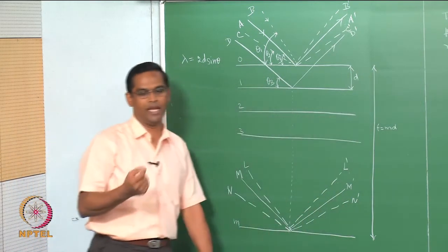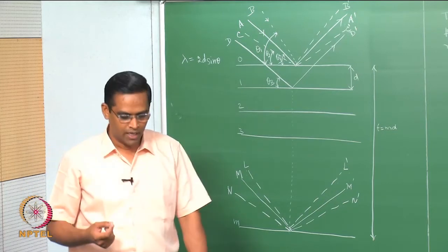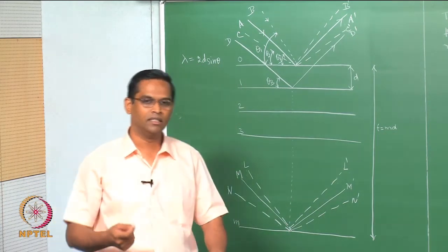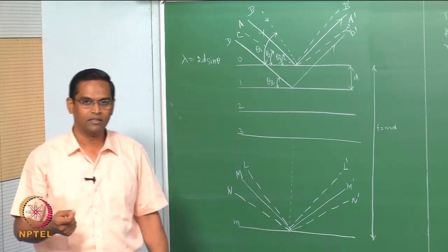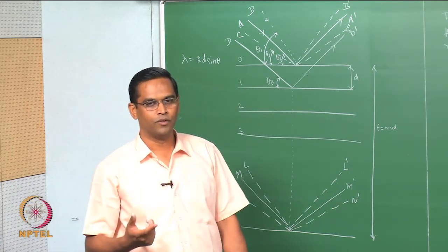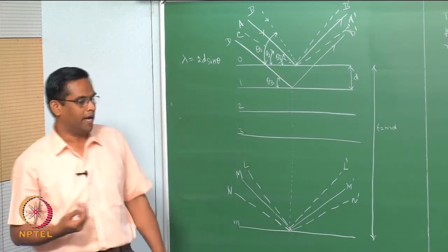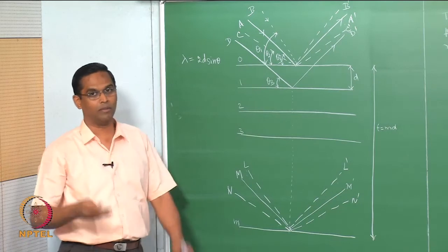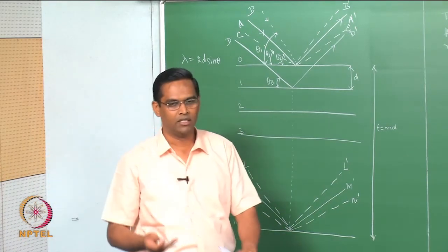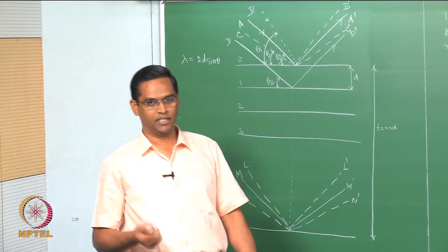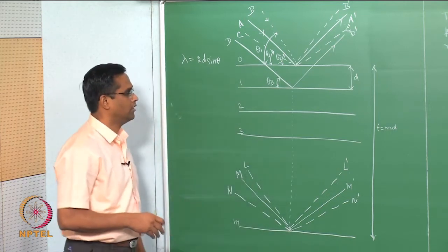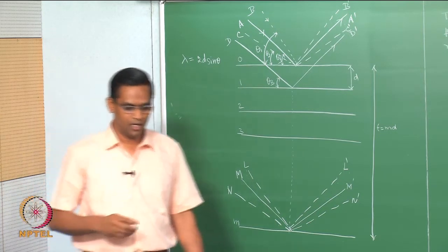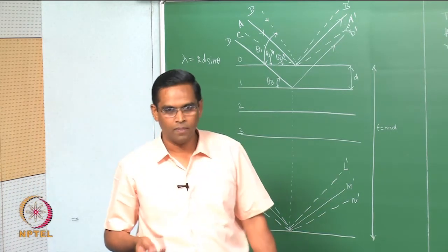That is the bottom line. There is a connection between the amount of out-of-phaseness and the crystal size. You have to keep this in mind when we talk about peak broadening. One of the primary reasons, the physical basis for peak broadening, is that there may not be a plane which will completely make the path difference out of phase.